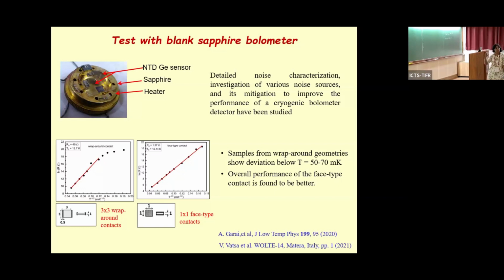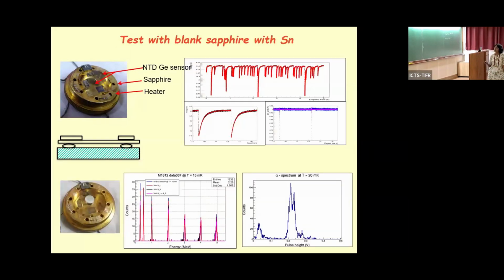Once you have a vacuum system and a cryogenic system to cool down, they all have their own vibrations, plus our lab is on the first floor, which doesn't help. Ground floor and basement labs help. So we had to understand all the noise characteristics. We did this with a sapphire bolometer. We mount a silicon heater and first check the phonon pulse response with these different sensors. These are the observed pulses.